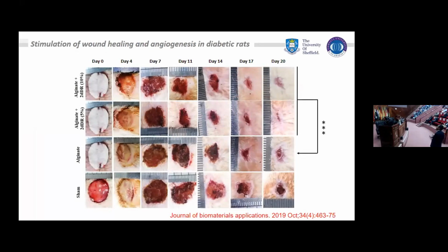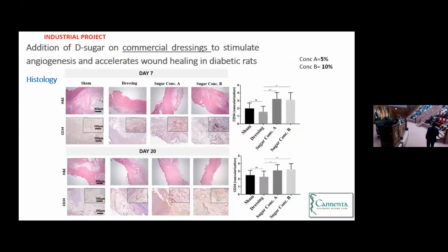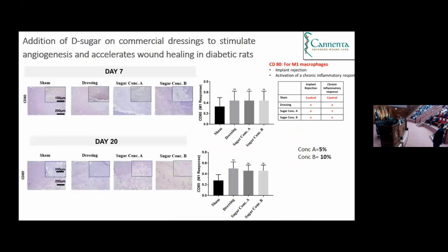What we have found is that on day 20, the wound which was treated with alginate was relatively closed, but this was completely closed when treated with alginate 5% and 10%. We've done extensive histological studies, H&E and CD34, to study the new blood vessel formation. And we have seen with CD34 relatively more blood vessels than when these were loaded with 2-deoxy-D-ribose, and a similar pattern on day 20 as well.